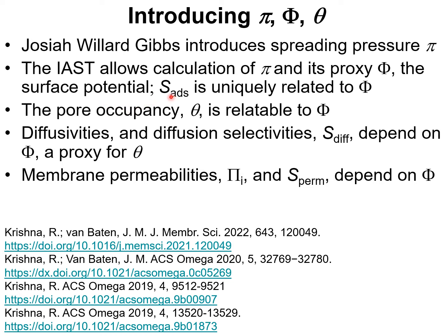We shall demonstrate using Monte Carlo simulations of mixture adsorption that the adsorption selectivity is uniquely related to phi. The occupancy of guest molecules inside the pores, theta, is relatable to the surface potential phi. The intracrystalline diffusivities and diffusion selectivities depend on the surface potential phi that can be considered as a proxy for the pore occupancy. The membrane permeabilities